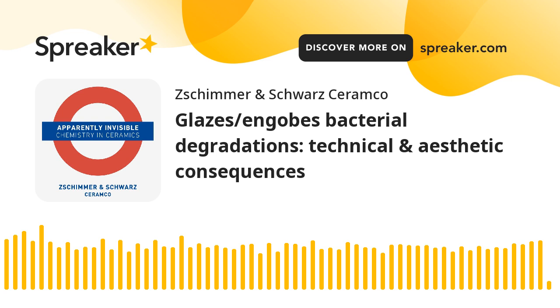And this is a condition that can lead to technical and aesthetic defects, such as, for example, holes and pinholes. Another problem that may occur is the improper drying time of the suspension. The improper drying time can promote a wrong integration between the layers of the ceramic tile that are applied one after the other along the glazing line. The lack of interaction between the layers, that is usually due to a chemical incompatibility, may be an important problem not only during the process but also after the firing cycle.